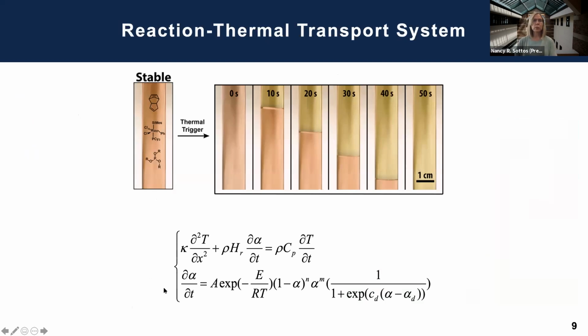And I just want to include too the governing equations for this. This is a reaction thermal transport system where T here is temperature, H_R is the heat of reaction. That's a property of the monomer. Kappa, rho, C_p are also properties of the monomer that determine the heat transport and the diffusion. And then alpha is the degree of cure. And then I show the cure kinetics for a typical thermosetting polymer here. But alpha also depends, of course, on temperature and an activation barrier, E. And so we're able to also analyze this set of governing differential equations to understand this reaction thermal transport process.